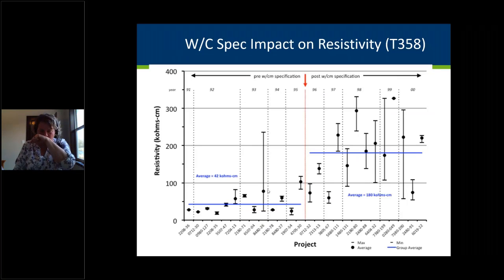Resistivity, a similar improvement. Pre is on the left of the red dash, post is on the right. 42 kiloohm centimeters pre, 180 kiloohm centimeters post. So really a great improvement in resistivity as we reduce the water cement ratio and increase the SCMs.